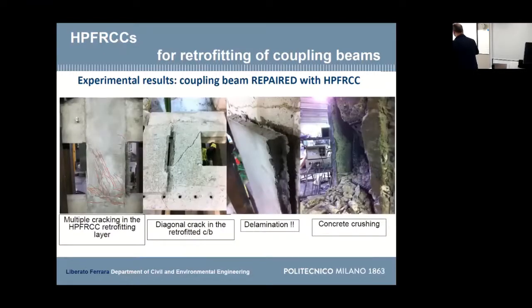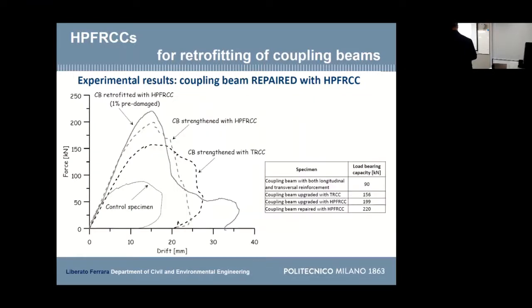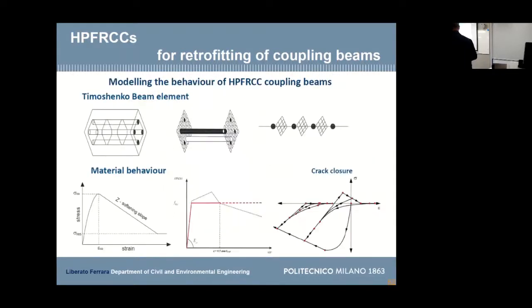And you can see this crack here, which was formed in the substrate. You see, it resulted into several multiple cracks on the retrofitting. So we were able to spread this localized damage into several multiple cracks. And this was the advantage of using this material for enhanced structural capacity. And compare the control specimen, non-retrofitted, with the retrofitted ones with different technologies and different amounts of pre-damage.